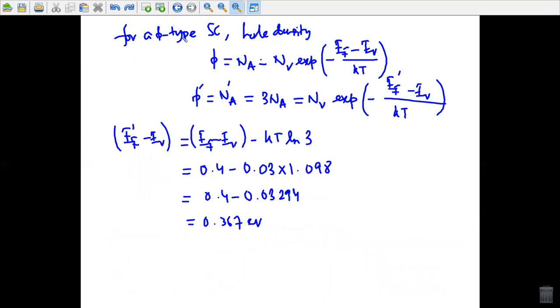So this is the solution. For a p-type semiconductor, the hole density is given by p is equal to Na, which is Nv exponential of minus (EF minus EV) divided by kT, and p prime is equal to Na prime, which is tripled, 3 times Na, that is Nv exponential of minus (EF prime minus EV) divided by kT. Comparing these two equations and removing the exponential term, we have EF prime minus EV is equal to EF minus EV minus kT ln 3, which is 0.4 minus 0.03 times 1.098, that is 0.4 minus 0.032, which finally turns out to be 0.367 electron volt.